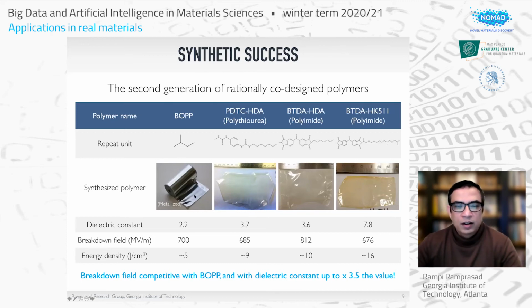And this is the biaxially oriented polypropylene, the standard material. These are the properties of those: dielectric constant 2, breakdown field about 700, energy density 5 joules per cc. That's the figure of merit we want to keep in mind. These are three new polymers that we were able to make in the lab, and these are actual pictures of actual films that were made, and breakdown measurements were made, 10 micron films, very exciting. Dielectric constant 2 to 3 times that of polypropylene, and breakdown field about the same or slightly better than that of polypropylene, translating to energy density of 2 to 3 times that of polypropylene.